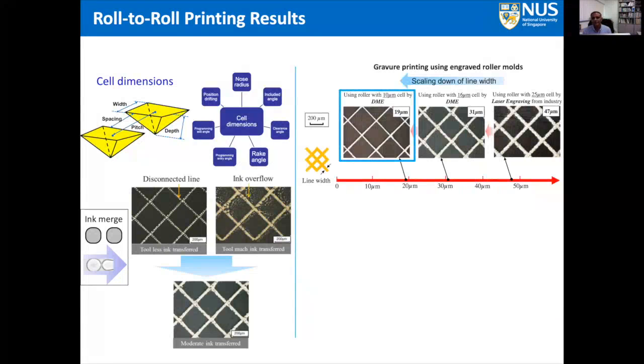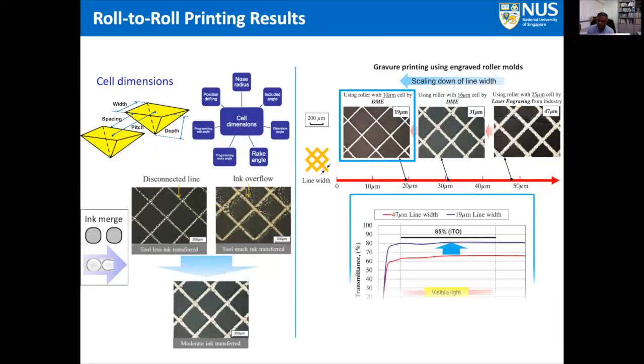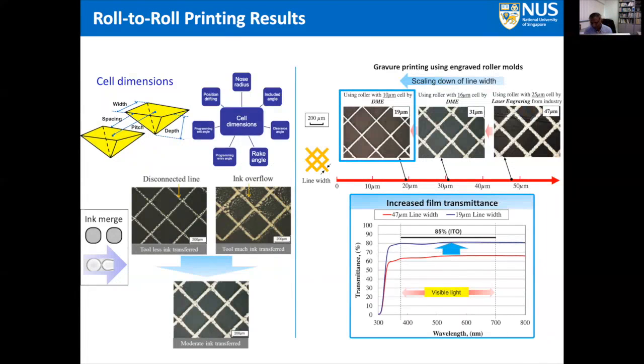So gravure printing using engraved roller molds tried to reduce the cell width from 25 micron to 10 micron. We also observed that the line width gets reduced from 47 to 19 micron, which is a significant reduction in the line width as well. And in this case, we can consistently see very good quality. Although the transmittance is not as good as that of ITO, some improvements still need to be done. If a good improvement can be made, probably in due course we will be able to replace the ITOs as well. Okay, meaning the indium tin oxide based touch screens can be replaced with metal mesh based